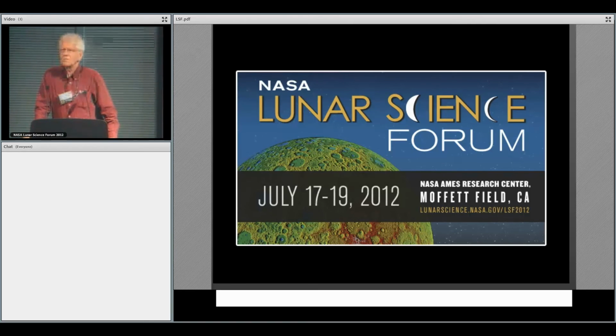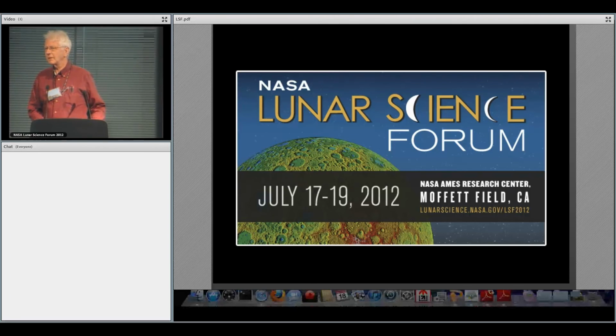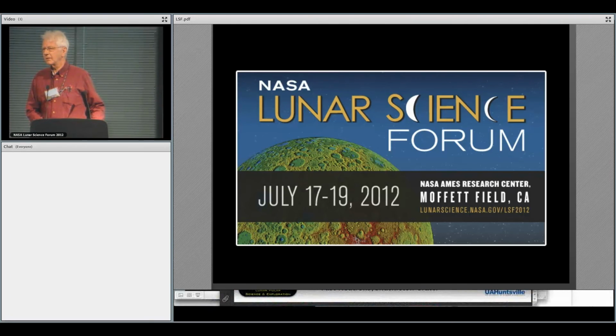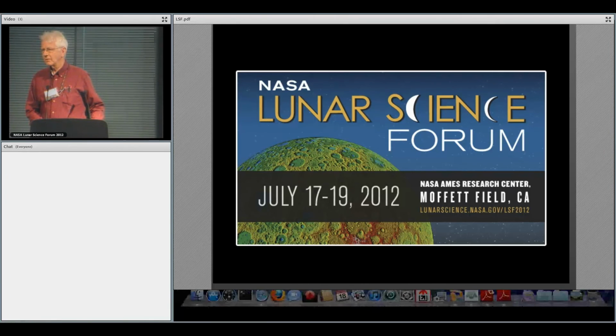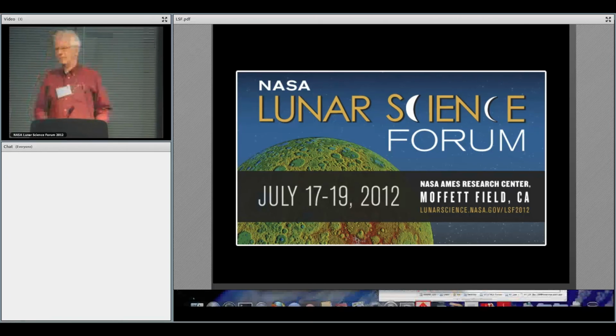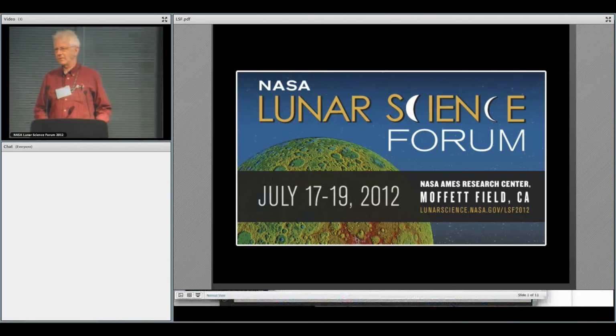Yes, I'd like to point out to you that there's a paper in Nature Geoscience that's coming out now, and it's based upon FTIR and SIMS work on lunar glasses. And we've shown conclusively that it's OH that's in there. So OH is present in various degrees from a few parts per million up to almost 1,000 parts per million in agglutinated glass. And so I think that although you have a good story to make here, the fact is that there's a little bit of difference between your starting material and the lunar soil itself. Yeah. I'd like to emphasize that.